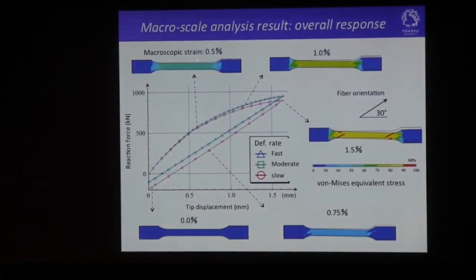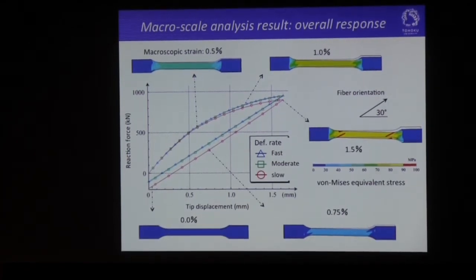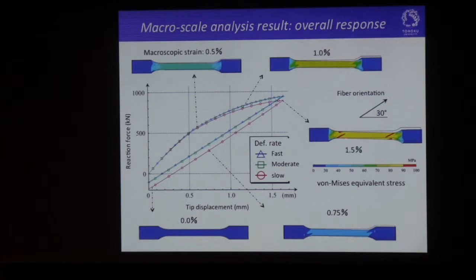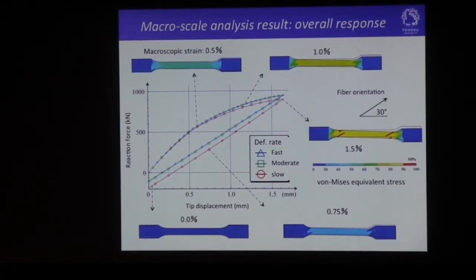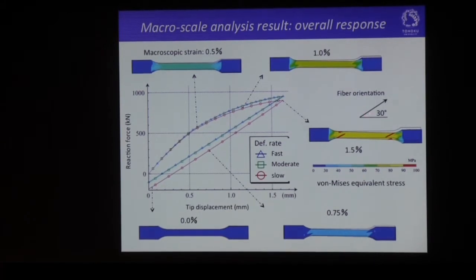Here is the macroscopic analysis result, that is the overall response. In this loading process and unloading process, we could have this kind of macroscopic deformation together with the stress distribution, which shows this kind of anisotropy, which reflects the fiber orientation here.